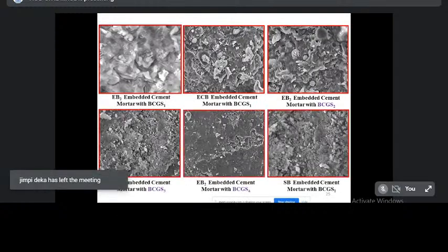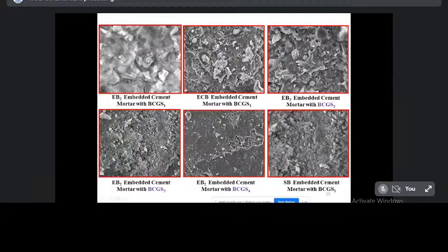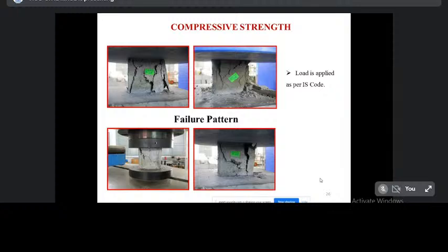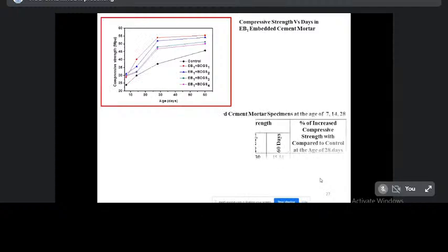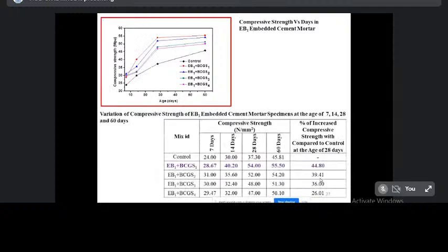So the next slide shows the SEM images of other bacteria mixed cement mortar specimens. This is the EB2 mixed cement mortar specimen SEM image. This is the Enterococcus embedded cement mortar specimen SEM image. From these slides, the white calcium carbonate deposition gradually decreases. And this is the compressive strength test and the failure pattern. Load is applied as per IS code. And this is the compressive strength value tabulation and graph.